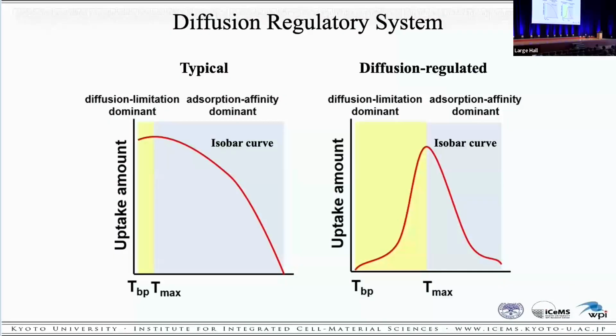This is the adsorption isobar representing guest adsorption. The left is the normal case where the adsorbed amount increases as the temperature decreases. On the right, in the MOF with a gate in the channel due to the local dynamics, at certain low temperature, the gate motion freezes and closes. And the adsorption does not increase anymore and begins to decrease.